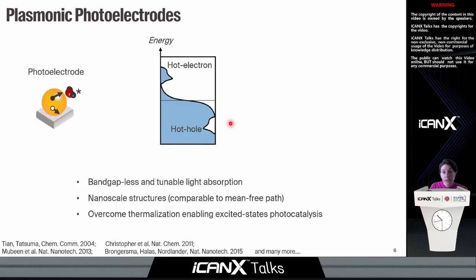So if we take now a metal which is a catalyst, as I mentioned at the beginning, gold and copper in our case, when the molecule adsorbs on its surface, it will create a number of adsorbate states. Typically, in equilibrium conditions, the electrons will transfer to a lowest unoccupied orbital or adsorbate state from these low energy electrons of the Fermi-Dirac population. However, now, if we have a significant proportion of hot carriers with high kinetic energy, we have the possibility of populating highly excited state orbitals, which then would result in a completely different chemical reaction pathway.